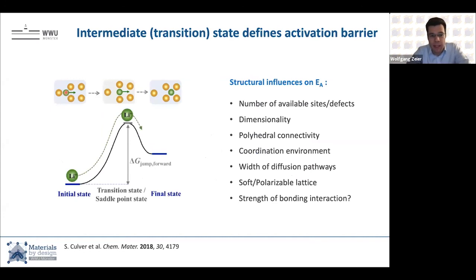So we have a lithium ion, in this case, sitting on a specific lattice site that needs to jump to an adjacent lattice site. By doing that, it needs to displace the lattice a little bit. This costs energy. This is our associated delta G. And after this displacement of the lattice, the ion jumps to its final state. And so there are a lot of structural parameters that influence the activation barrier, the energy landscape of these materials.